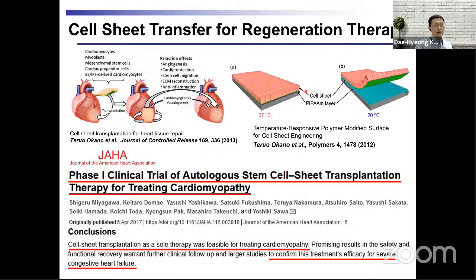They cultured the cell sheet on the poly(NIPAM) substrate. Such cell sheets can be either cardiomyocytes or mesenchymal stem cells. If the temperature is changed from body temperature to a lower temperature, such as 20 degrees Celsius, then the surface property of the PNIPAM layer is changed. Due to that changed surface property, the cell sheet can be delaminated and transfer printed on the target region of the heart.